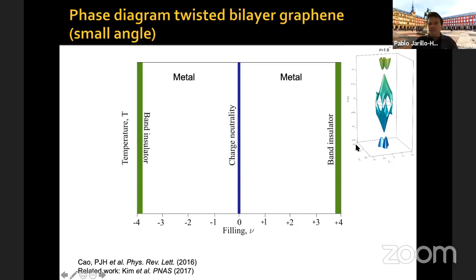When you reach those points, the top of the conduction band or the bottom of the valence band, then you have band insulator behavior from the electronic transport point of view, because you reach this band gap before you can, with your Fermi energy, move on to your remote bands. Okay, so you have band insulator states. These band insulator states are of single particle origin, so they are well understood. We saw them some time ago and they have been reproduced by many people.